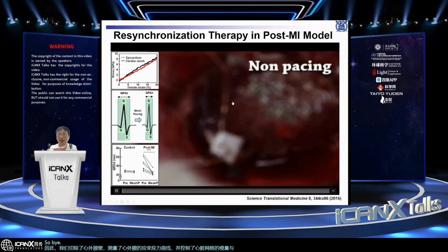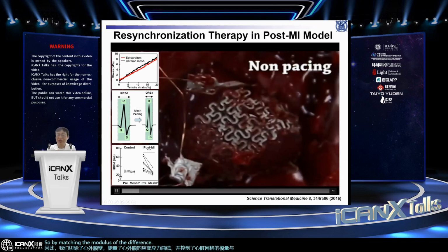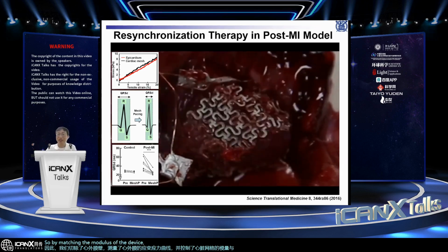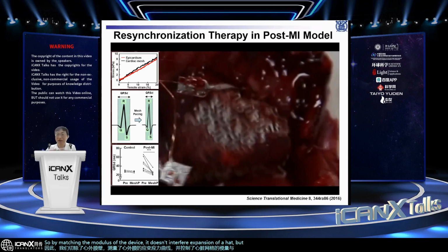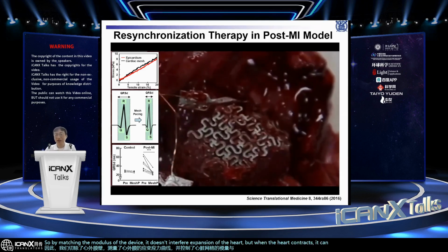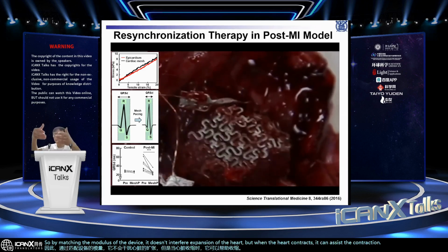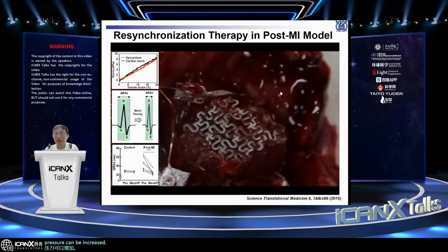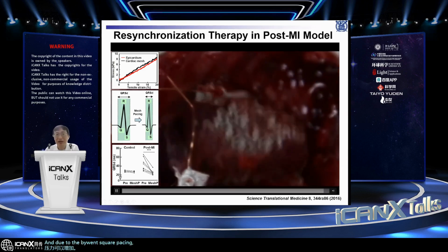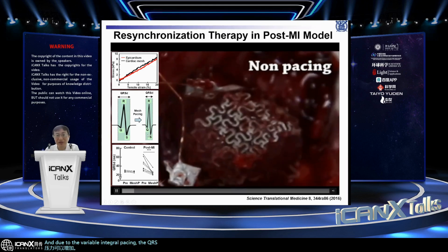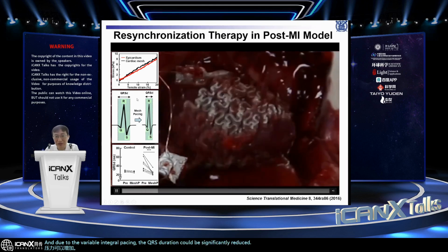So by matching the modulus of the device, it doesn't interfere with the expansion of the heart, but when the heart contracts, it can assist the contraction, so the blood pumping pressure can be increased. And due to the biventricular pacing, the QRS duration could be significantly decreased.